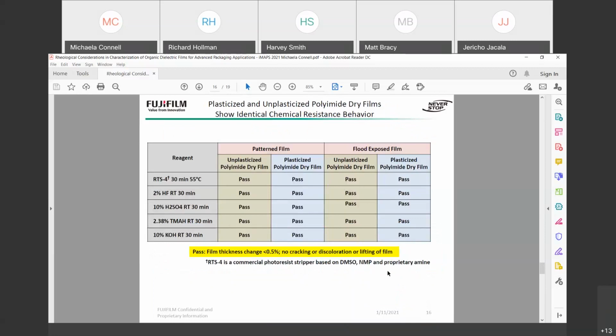Chemical resistance was also performed on both plasticized and unplasticized films, with both patterned and flood exposed films, after a 170 degrees Celsius, 2 hour cure. We used 5 different chemistries. We used RTS4, which is a commercial photoresist stripper based on DMSO, NMP, and a proprietary amine. We also used 2% HF, 10% sulfuric acid, 2.38% TMAH, and 10% KOH.